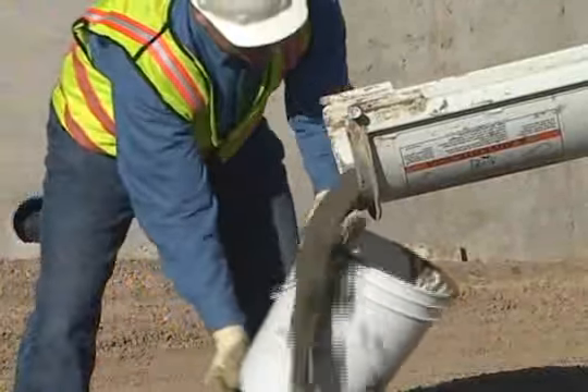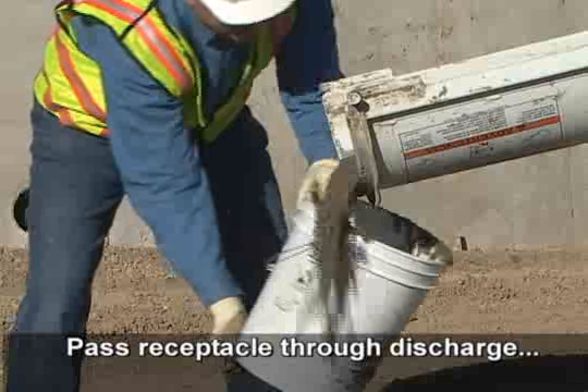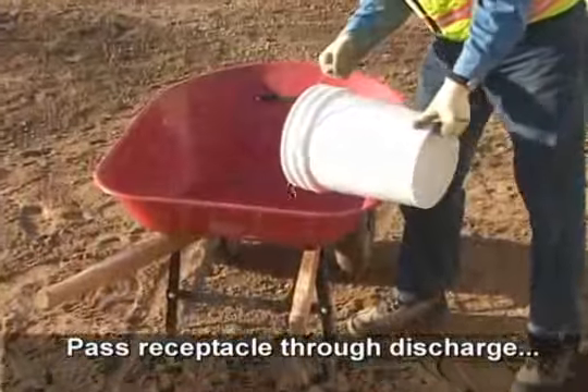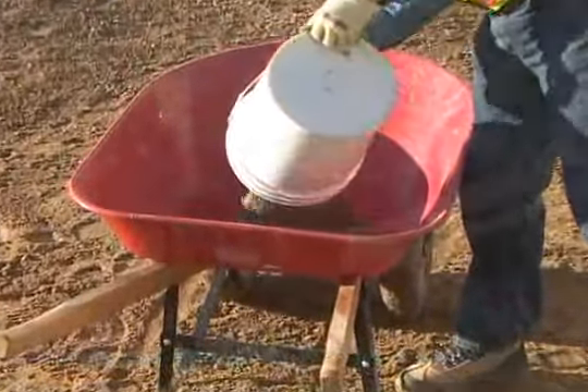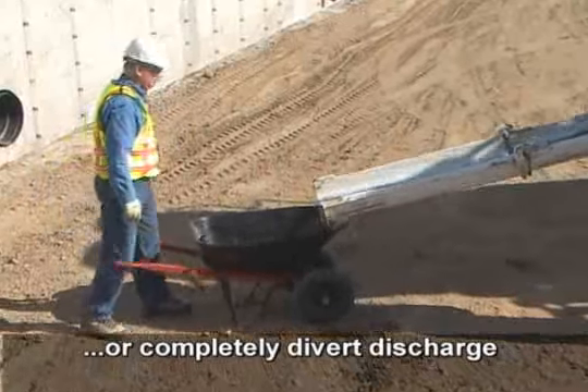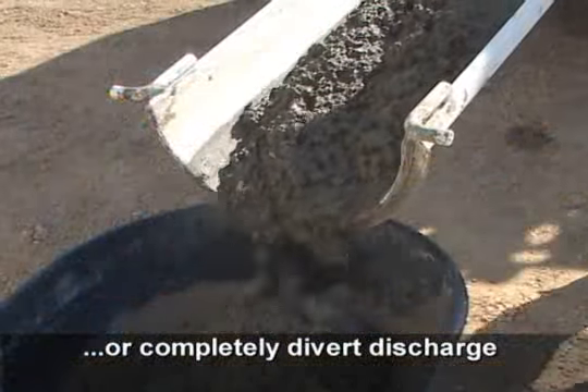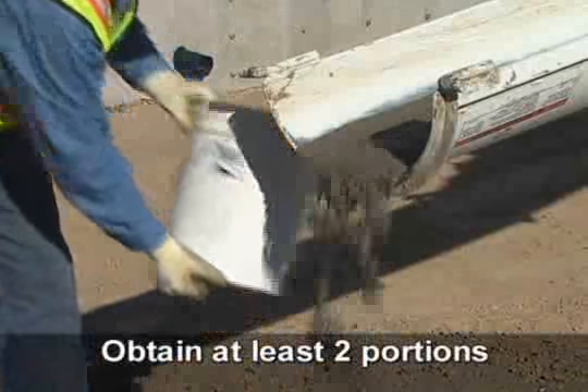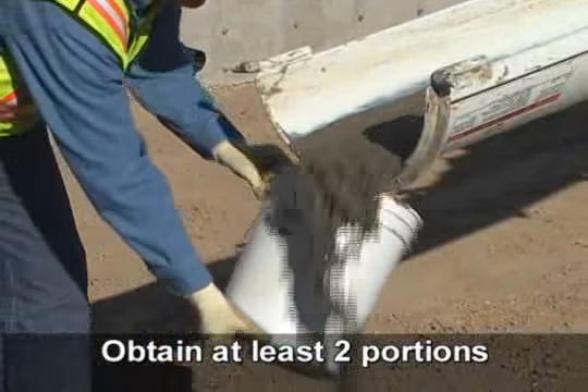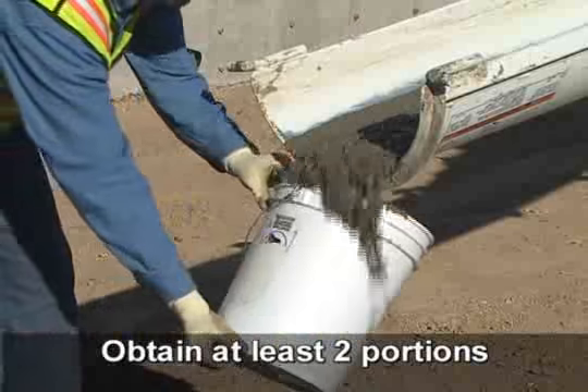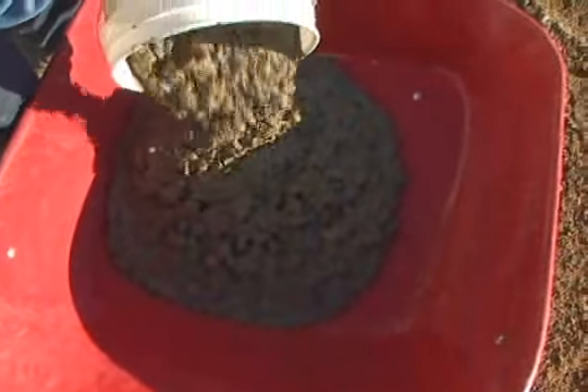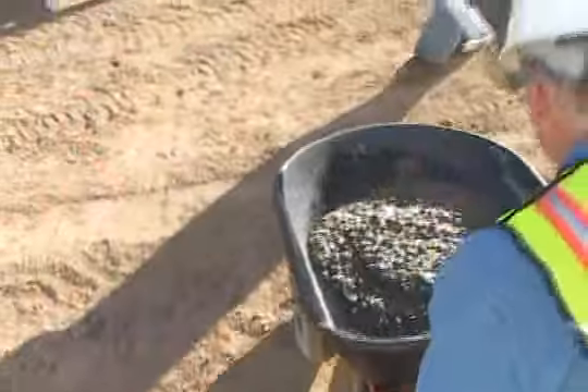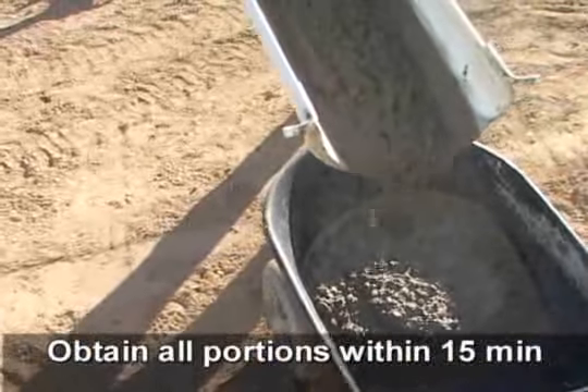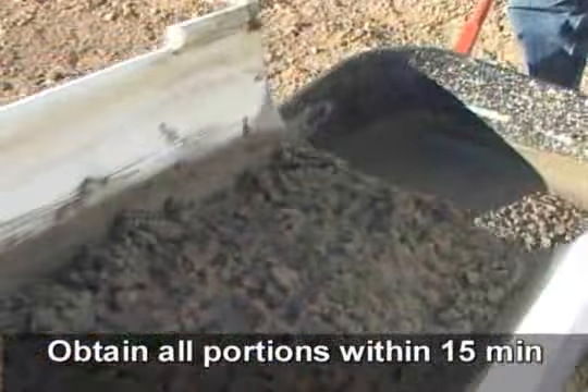Concrete can be sampled either by repeatedly passing a receptacle through the entire discharge stream or by completely diverting the discharge into a container. Obtain 2 or more portions of material at regularly spaced intervals from the middle of the load. The elapsed time between obtaining the first and final portions of material shall not exceed 15 minutes.